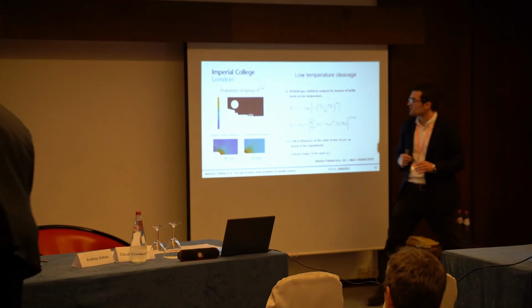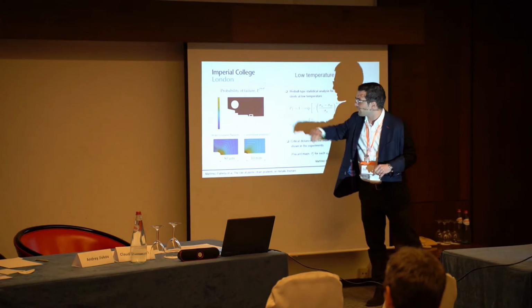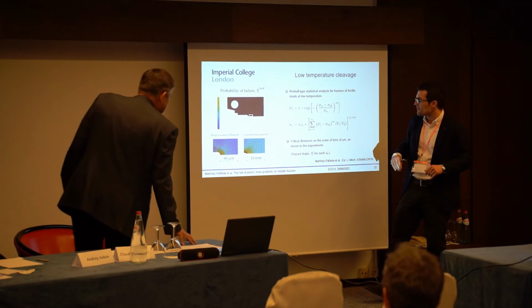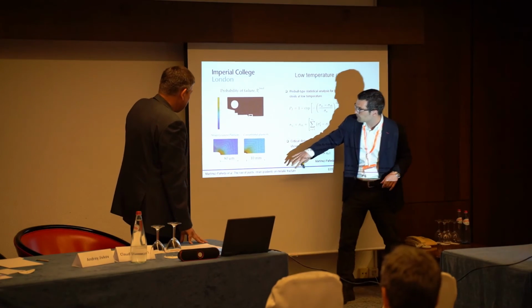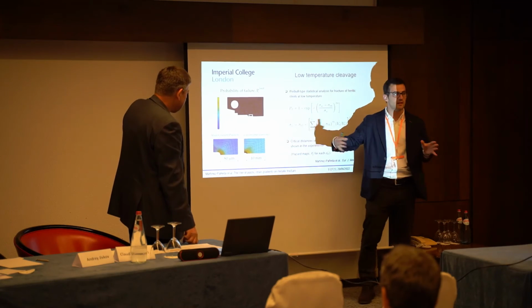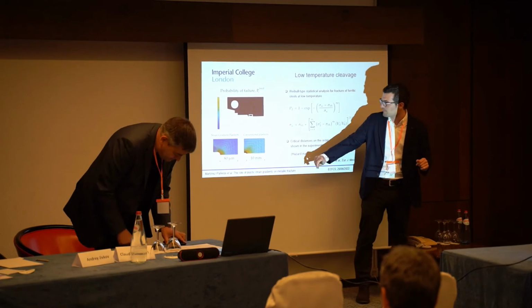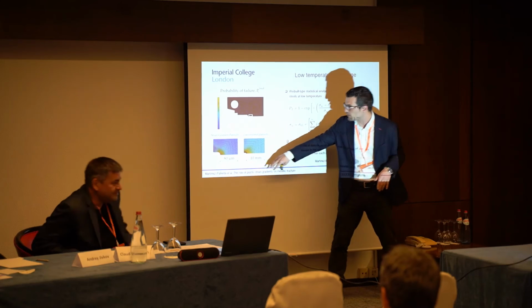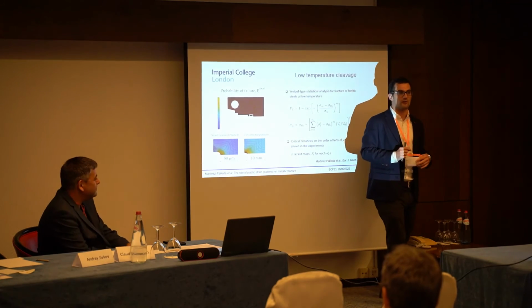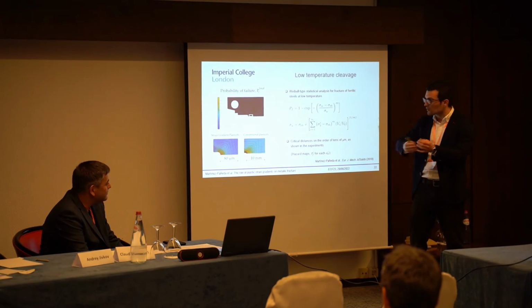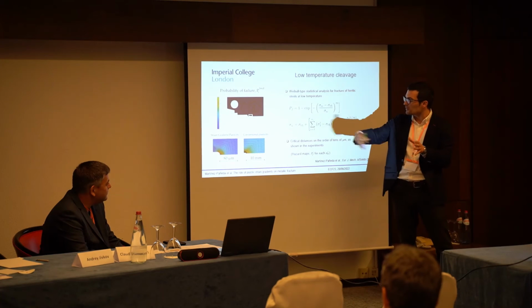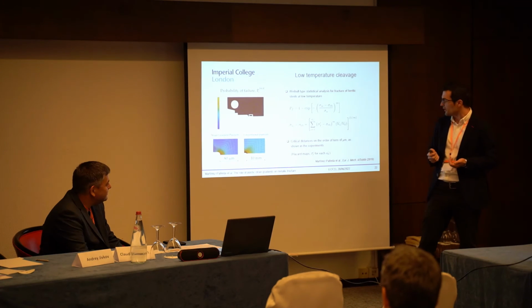But what I think is more interesting is that we computed the local probability of failure for a given Weibull stress, and we saw that the probability of failure was typically spread over tens of millimeters for conventional plasticity, while it was constrained to tens of micrometers for gradient plasticity. And from the experiments, it seems that the critical distance for low temperature cleavage is within tens of micrometers, so it seems to have been very interesting.